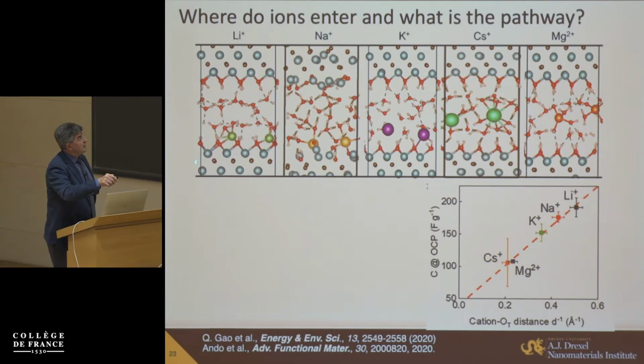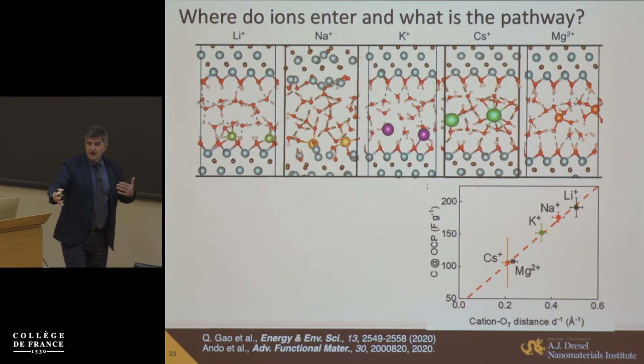And the reason is that those are MD simulations done by our Oak Ridge colleagues, Paul Kent and Dean Jiang. Here, you see lithium and sodium will actually come to the surface of MXene, and there will be polarization, and there will be more charge transfer compared to, say, potassium or cesium, which will stay far away. So what they actually showed here is that taking a distance between the oxygen on the surface and the cation, you can actually predict there is a kind of almost linear dependence how much capacitance you have, because this is really like polarization. It's double layer capacitance, but there is partial charge transfer.